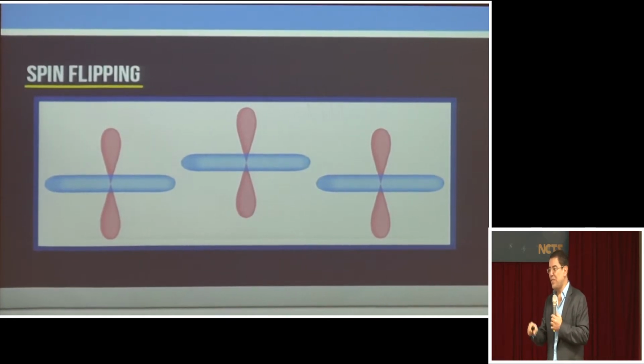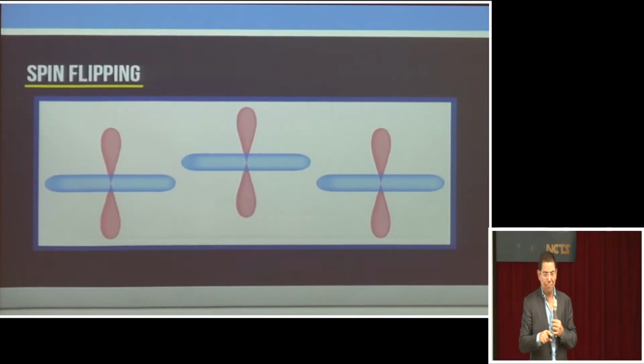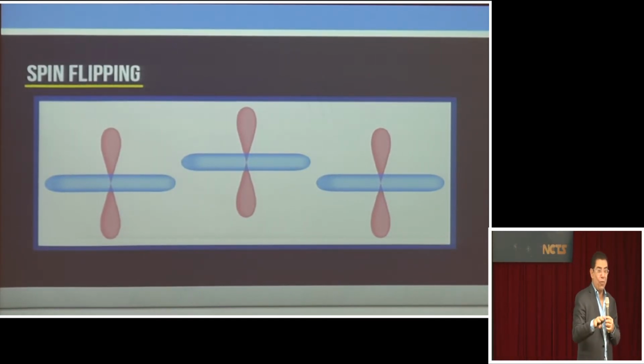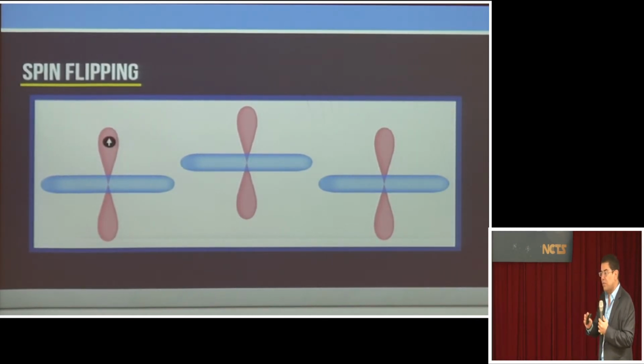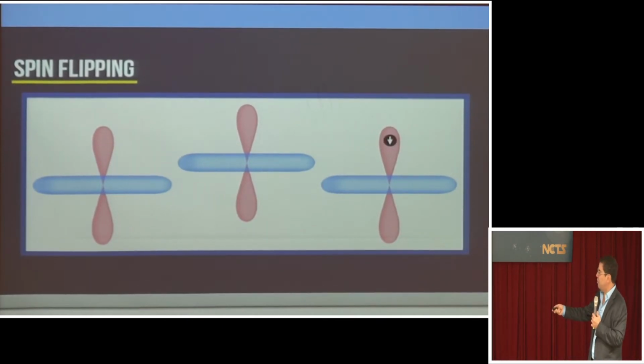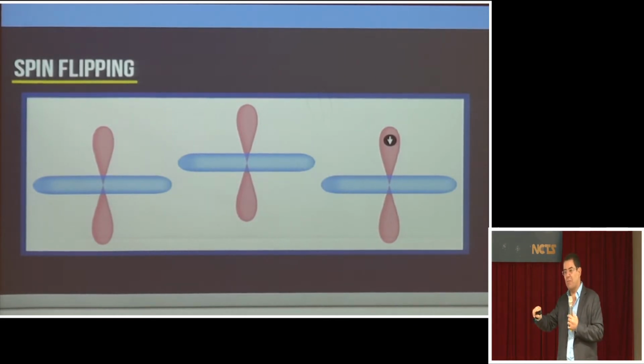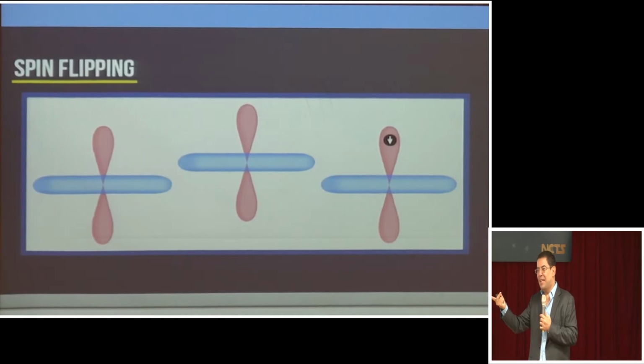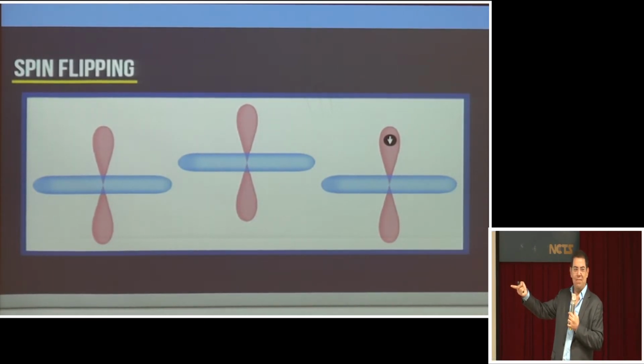This does not happen in 3D materials. This is very particular of lower dimensionality, and of the fact that this structure is not flat. What this allows is something very interesting that you don't see very often: an electron with spin up can move to the atom on the same layer with spin down. So if you look at just one layer of atoms, it looks like you have a spin flip in the hopping process. And this comes about in these materials because of this asymmetry that they have.